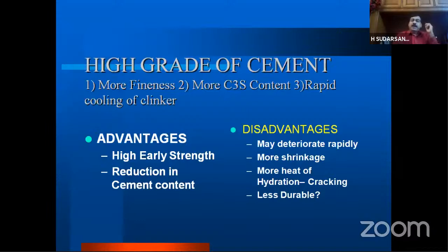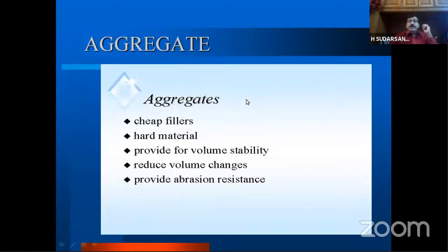But high grade cements have their own demerits because they may deteriorate the structure rapidly. We have problems with shrinkage because it causes greater heat of hydration and cracking, as it's very fine cement, and that's why the structure becomes less durable. So all these disadvantages are there. So you have to properly decide which grade of cement you have to use, depending upon the purpose for which you are designing the structure. If you are designing a structure for underwater, say you need high early strength, then you have to go for a high grade cement.